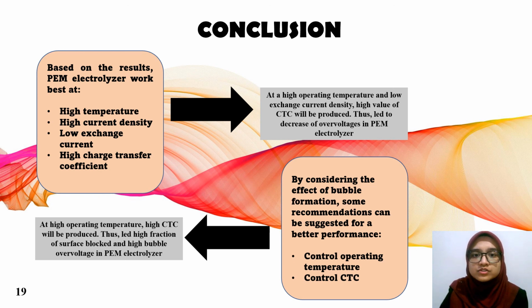If we want to consider the effect of bubble formation, some recommendations can be suggested for better performance, which is to control the value of operating temperature and also CTC. This is because at high operating temperature, high CTC will be produced. Thus, it will lead to a high fraction of surface blocked and high bubble overvoltage in the PEM electrolyzer, so it will degrade the performance of PEM electrolysis.